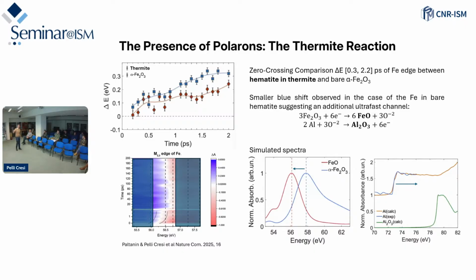Okay. In the thermite alone, obviously you can't. In the hematite alone, you don't get reduction. Whereas in the thermite, you can get it. Exactly. In that case, the formation of the polaron probably also reduces the possibility of having the reduction of hematite, and they are competitive. They're going in opposite directions. Exactly. That was our interpretation.